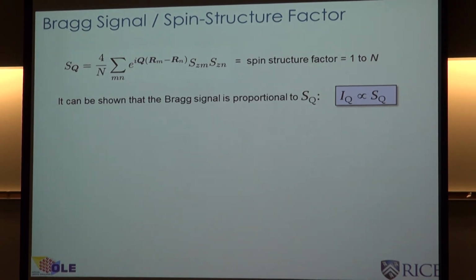So it turns out that the Bragg scattering actually measures something called the spin structure function. And this is the spin structure function. This is, again, the reciprocal lattice vector. This is the vector to a particular lattice site and to the nth lattice site. And this is the magnetization. And so if you had perfect antiferromagnetic order, this structure factor would be equal to N. Or without this normalization, it would be equal to N squared. If you had perfectly random order, if you had no order in the system, the spin structure factor would be 1. So we expect to measure something between 1 and N. And if you normalize the Bragg scattered signal appropriately, the intensity that you measure will give us exactly something between 1 and N.